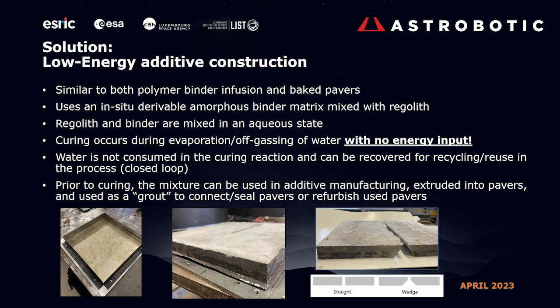low energy additive construction. It's very similar to what people are talking about with a lot of the polymer infusion bricks, but it's what I would call an in-situ derivable amorphous binder matrix mixed with regolith. So it's not a polymer, it's a different binder agent. And crucially, for that binder agent, we're mixing it as an aqueous solution with the regolith, where we're adding water to the binder, creating almost like a paste, a very, very viscous, relatively high regolith content paste that we are using and then forming into whatever we want to make.